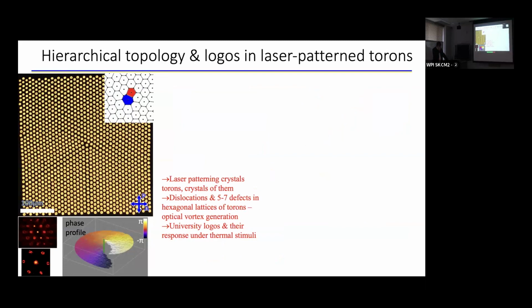Now it's important to understand that the structures of torons and skyrmions in liquid crystals can emerge in different locations as we quench the material from the isotropic state. And they can crystallize, but we can also use laser tweezers to define the locations of such topological solitons. So in fact, in here you can see an example of how an array of such topological objects can be formed with crystalline ordering that also has a 5-7 defect in this lattice that can be used as an example to generate vortices in light.